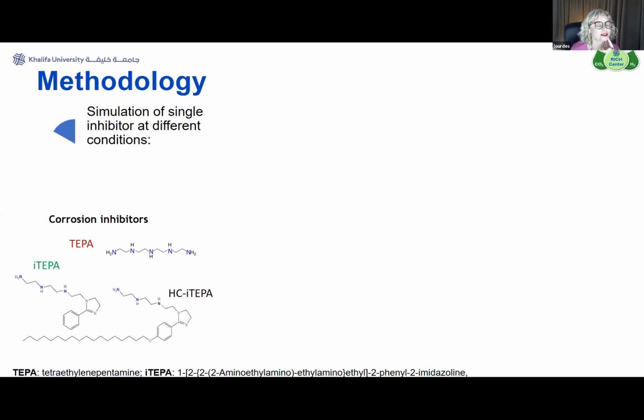There are two molecules here that are used experimentally. One is what we call the HC-iTEPA, in which we have the tetraethylenepentamine chain here, two heterocyclic rings, and then a lone alkyl chain. This is the one that in the literature shows to be effective. There are some other studies in which they have used what we call TEPA, which essentially is this part of the HC-iTEPA molecule. And we propose to study ITEPA, in which we cover the tetraethylenepentamine group, but also the two cyclic groups. In this way, we can isolate the effect of having just TEPA, the cyclic groups, or the effect of the alkyl chain on this absorption.